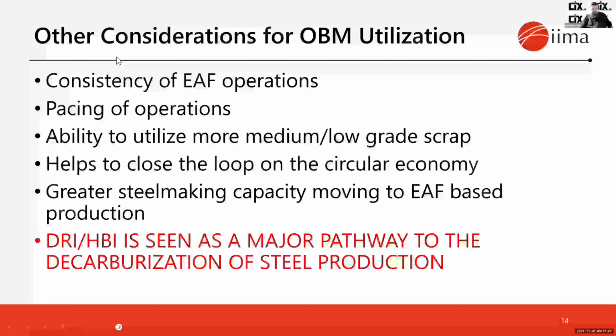Other considerations for the use of ore-based metallics, well, it greatly aids with the consistency of EAF operations, hitting the same sort of melting chemistry. It's very effective for pacing operations in the steel plant. It allows you to utilize more medium and lower grade scrap, helps to close the loop on the circular economy, and greater steelmaking capacity moving towards EAF. So we still see a need for the ore-based metallics. So as a result, DRI and HBI are seen as a major sort of pathway to the decarbonization of steel production.